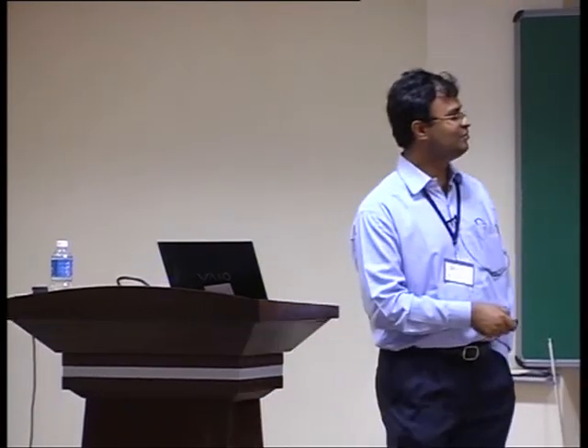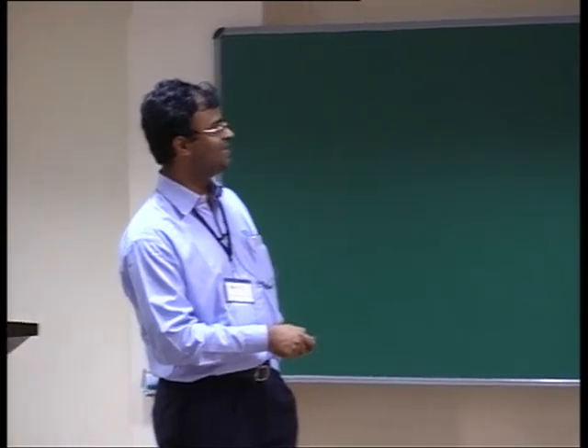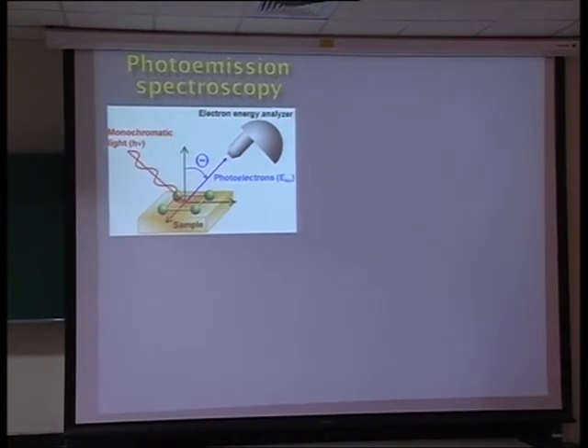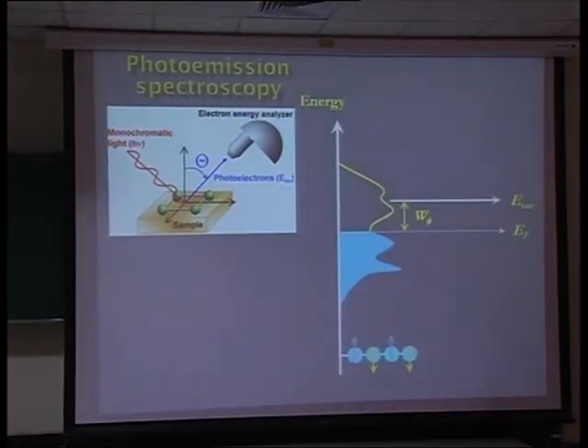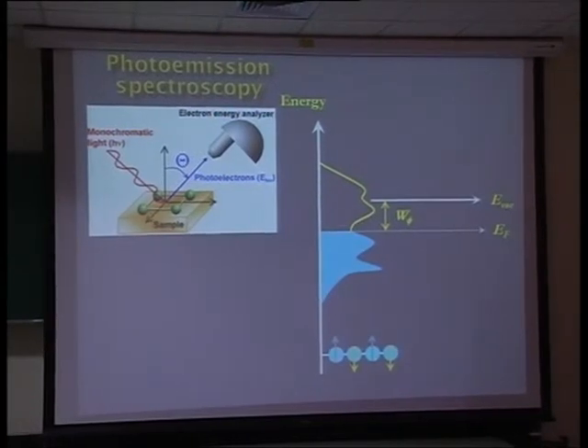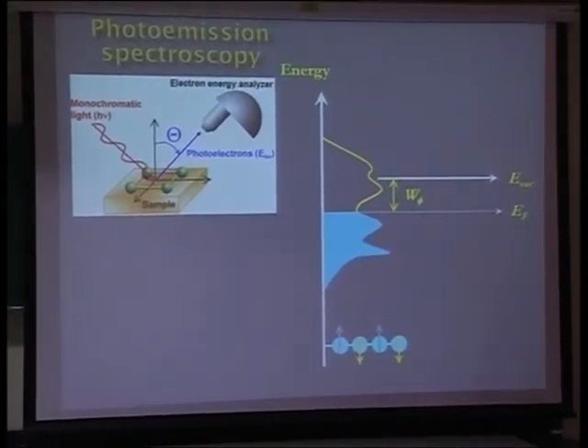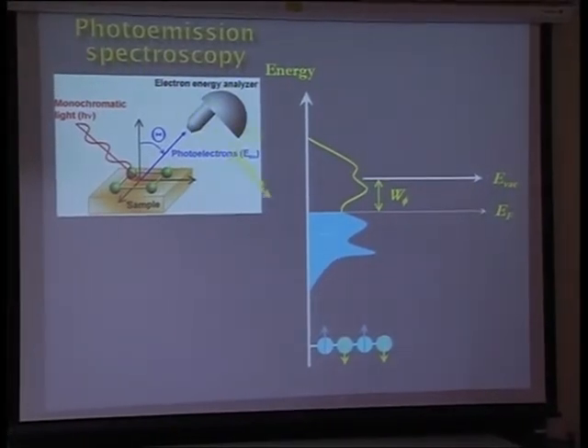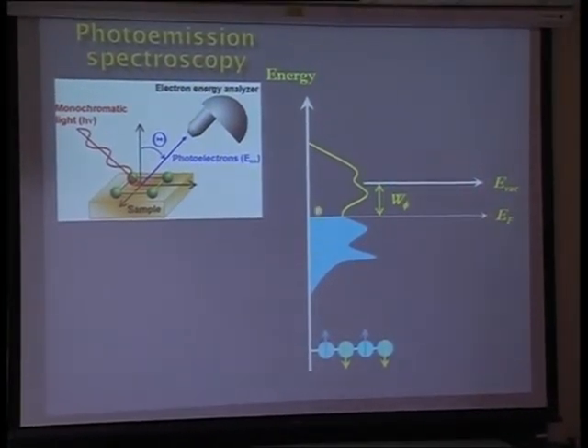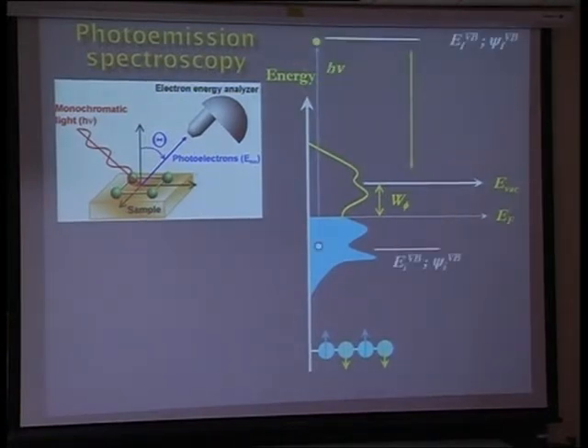So in photo emission, what we do is that you shine a sample with some light, the electrons are excited, and you put a detector here, and you detect the kinetic energy of the electrons. So if this is your electronic structure like a valence band, core levels, and so on, what happens is that you put some photon of energy hν, and the electron energy increases due to the absorption of this hν. And if you determine the kinetic energy of the electrons which are coming out, you can immediately find out the binding energy of the corresponding electron that comes out.